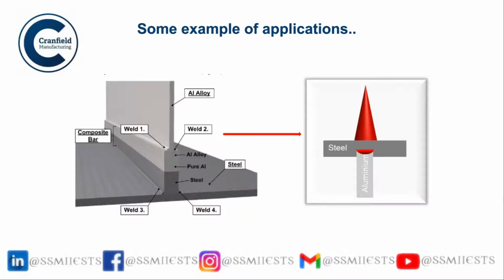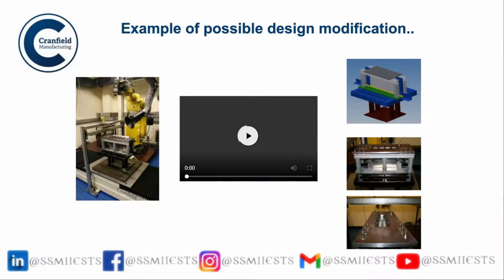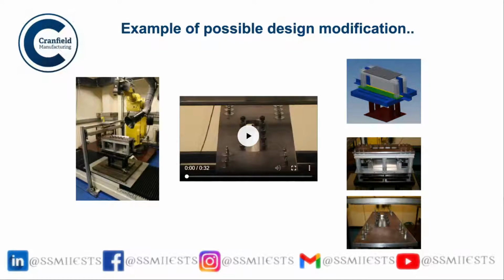This is steel and the aluminium should go inside, and when the laser comes like this, you see, a design modification was required in order to make it suitable for a specific application. Then the heat should pass through the steel and form the joint here. This is done using a setup in our lab, and basically a T-joint is formed at the end of this particular process.